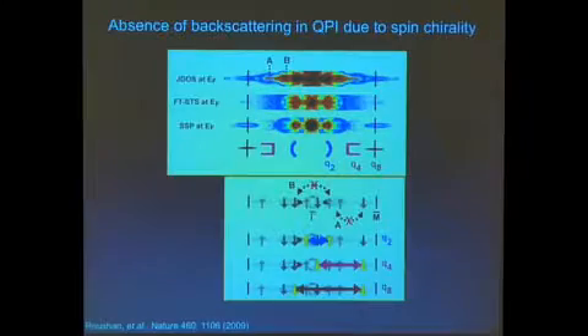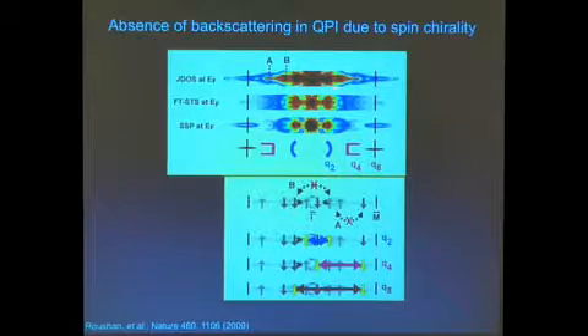So let me zoom in on that. So these are the high symmetry directions in the data. The reason these are interesting to us is that these are telling you about wave vectors in which you can scatter, if you like, from an electron that's moving forward to an electron moving backward with the same momentum, but now it has to have the opposite spin. And you can see that those wave vectors, which you might have expected to be in a simulation, are basically missing in the experimental data. But if you put in the spin texture and run this sort of simulation again, you get all the little details that this data produces.